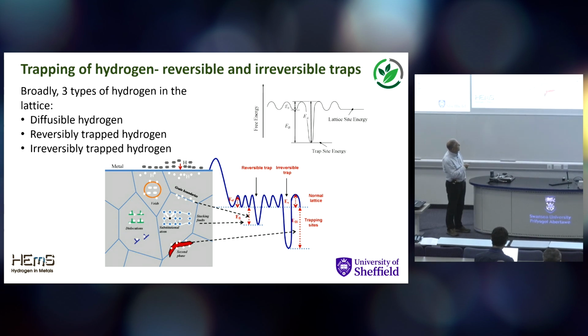So this diagram here is showing you the free energy, and this is the normal lattice site free energy. If we have a deep trap, as it's called, the hydrogen loses energy going into it, and it's quite happy there, and it doesn't want to come back out. That's called an irreversible trap. So if we can get the hydrogen in there, it's basically out of harm's way. But there are also these reversible traps, which are typically dislocations, grain boundaries, and so on. The energy does go down, but it's not far enough, and the hydrogen can jump back out of that and cause all sorts of problems, such as hydrogen embrittlement.